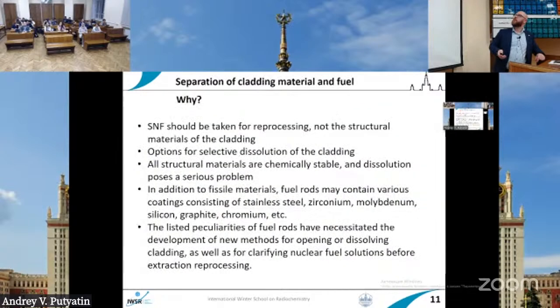Okay, so why is it better to separate the cladding material? First of all, as I mentioned, the cladding itself consists of elements that can form precipitates during the reprocessing, like zirconium. There are a lot of problems with zirconium. During the first cycles of the extraction, we need to add special water-soluble ligands to avoid extraction of zirconium into the organic phase. So it is better to avoid the presence of zirconium in the solutions.